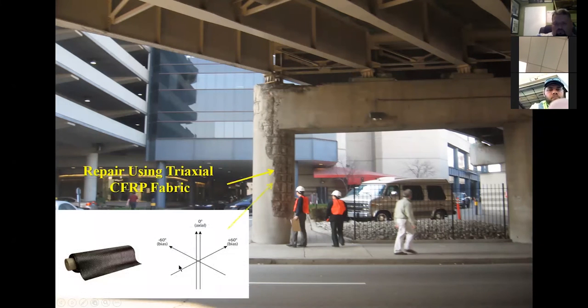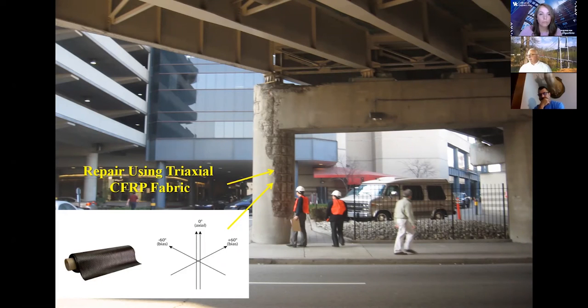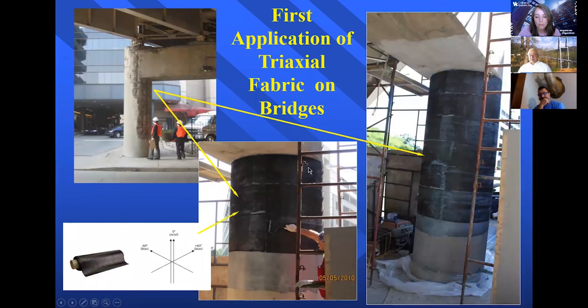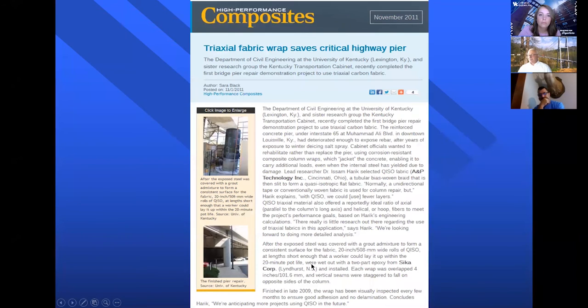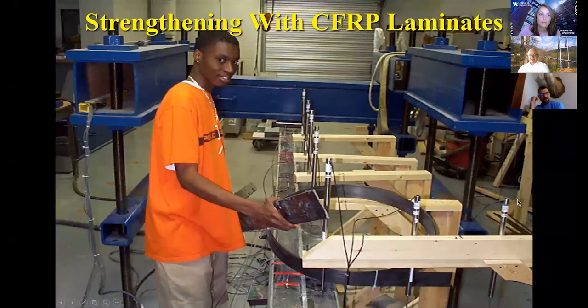We decided to use what's called the Tri-Axial Fabric. This is used extensively in the aerospace industry, both for civil aviation as well as military aviation, right? So this Tri-Axial Fabric has fibers that go in 3 directions. That saves us quite a bit of time, because with one fabric, I can provide reinforcement for both the vertical direction and the hoop direction around the pier. And this was the first time ever that such a fabric was used on any civil structure, and it also received quite a bit of attention.